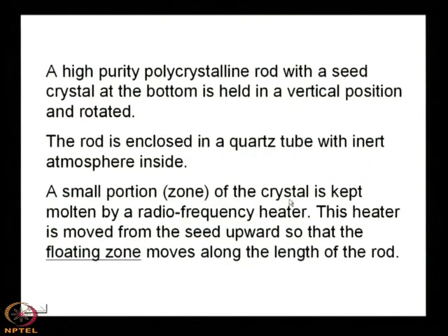A small portion of the crystal is known as the zone, Z-O-N-E. So, the name of this technique is float zone technique. Zone comes from this concept that a small portion of the crystal is kept molten by an RF heater, radio frequency heater. This heater is moved from the seed upward, so that the floating zone moves along the length of the rod. So, the float zone comes from this concept that the zone moves.